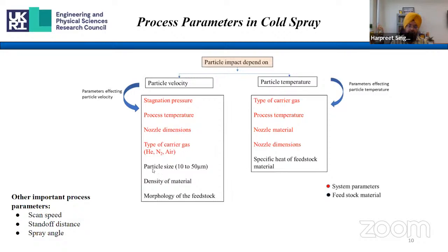And of course this particle velocity depends on particle size as well, density of the material, and morphology of the feedstock and so on. And particle temperature will definitely depend upon the carrier gas and process temperature, nozzle material, nozzle dimensions, and specific heat of the feedstock material. Among these, some of these are system parameters, these red ones, and then we have feedstock material parameters as well. There are some other very important parameters which we should not skip here. One is the scan speed, like what is the travel speed of your gun relative to the substrate, and standoff distance, and then spray angle. All these parameters play a significant role in dictating the properties of your deposits.